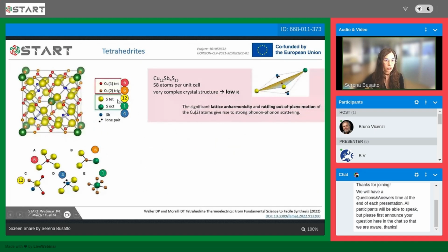This is the crystal structure of tetrahedrite. It's a very complex unit cell. It's composed of 58 atoms per unit cell, and this is one of the reasons why the thermal conductivity of this mineral is so low. And the other reason why it's so low is because there is a rattling motion of some copper atoms, resembling those of some other thermoelectric materials like skutterudites and clathrates, that also contribute to giving strong phonon-phonon scattering and to lowering the thermal conductivity.